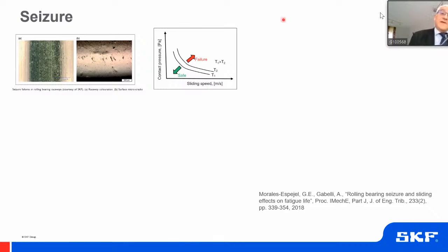And this failure is a thermal failure, produced by high temperatures. There is a sort of line here that you cannot cross because the contact will fail. And it depends obviously on the temperature you are doing the experiment at as well, and the lubricant and the additive and many, many other aspects, the roughness as well. But in reality, for every contact, there is one line here, and that is called the transition diagram. Now, it is very important to develop these transition diagrams for specific machine elements like rolling bearings or gears.